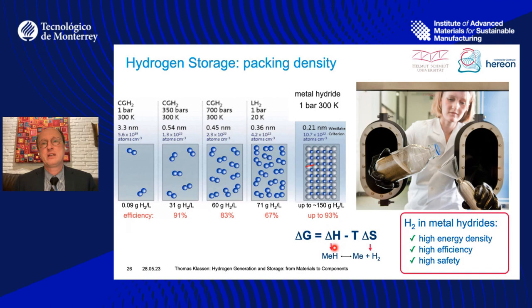So the chemistry says, let's form a metal hydride, so hydrogen's bond and stored. The entropy says, no, it's much better to have a hydrogen gas, because the gas has much more entropy. And so we separate again. And at low temperature, the chemistry will win, hydrogen is stored. At high temperature, the entropy will win, and hydrogen is released. So it's fully reversible. And the 7% loss are actually the bonding heat.